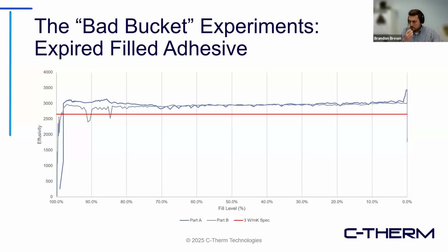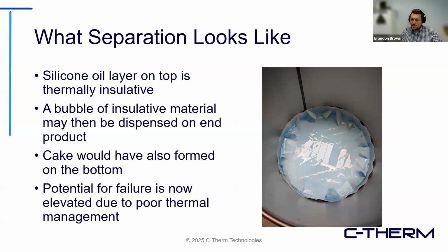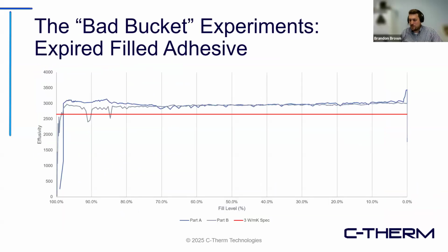On a following slide, I've got a picture of one of the barrels, but here, stay on the slide, please. The data clearly shows that both parts suffered from settling, where the top layer consisted of insulating silicone oil. And right at the end of the barrel, right at 0%, you can see that this is where the sensor was starting to see the cake that had formed. So with proper monitoring, it could be possible to bleed off the top and use the middle portion of the barrel, which is still good. And since this is a 200-liter barrel, the material cost could be, for example, over $10,000 per barrel. And so there's great potential for savings here. Next slide.